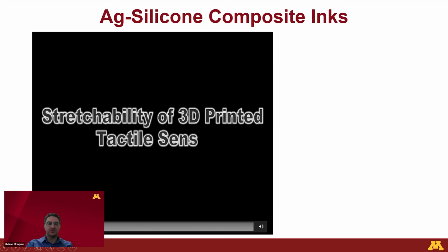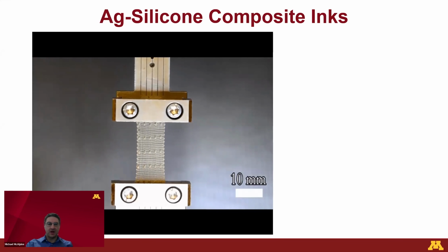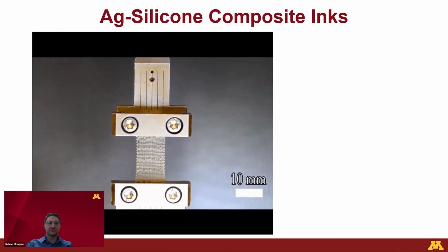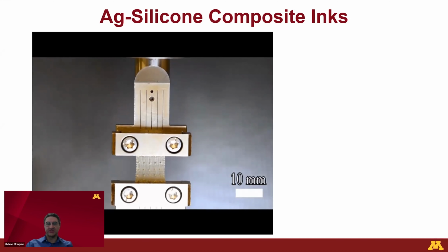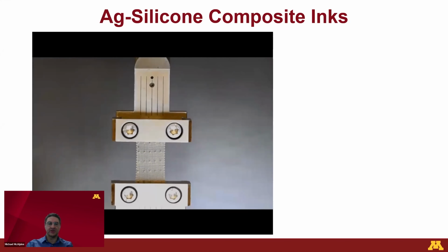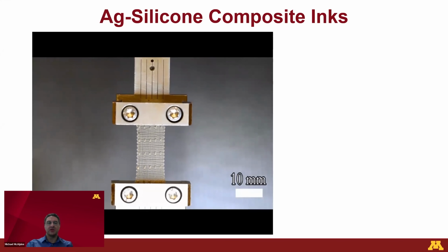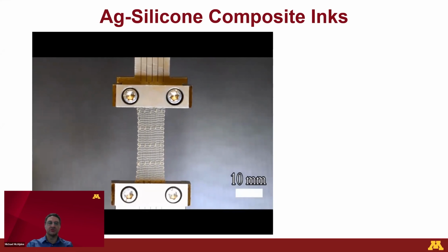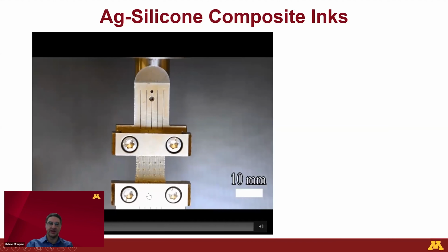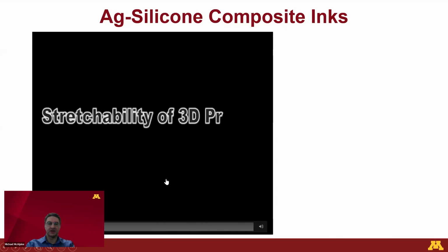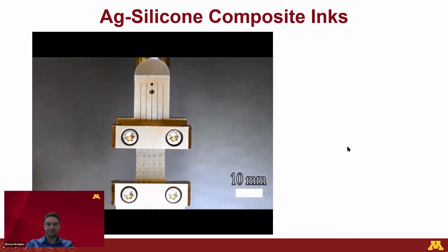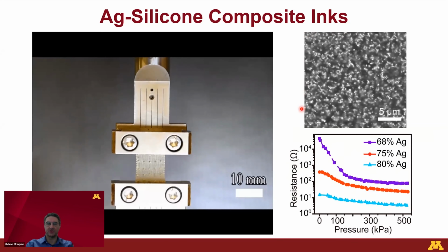So here's an example of our ability to print a type of ink, which is a composite between silver particles and silicone. And so silicone itself is actually difficult to print on a conventional printer because it's a thermoset rather than a thermoplastic. So it doesn't really melt the way a plastic does. So that by itself is difficult. But then what we can do here is mix into that silicone precursor ink some silver particles, which makes it not only a stretchable material, but also electrically conductive as well by having silver mixed in it. You can sort of see that with the color here. It's not clear and transparent like traditional silicone. It has that sort of gray color to it.